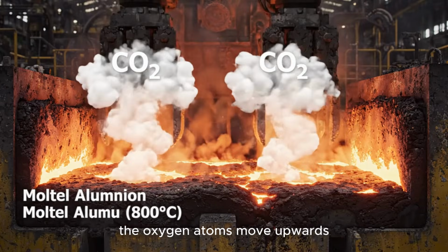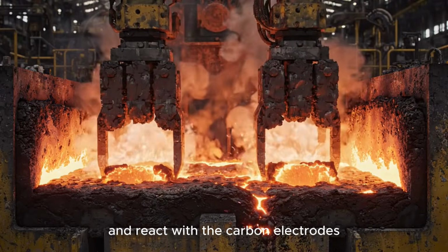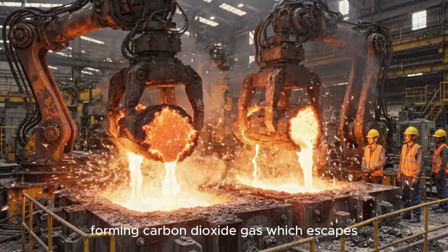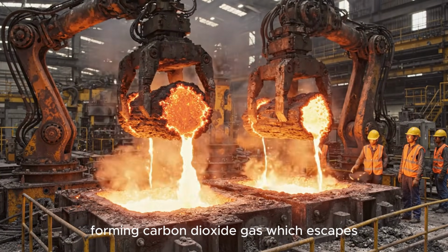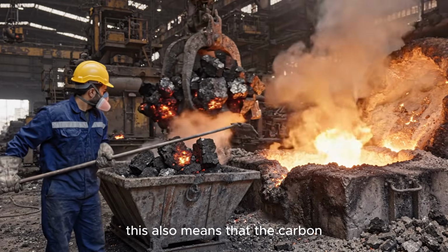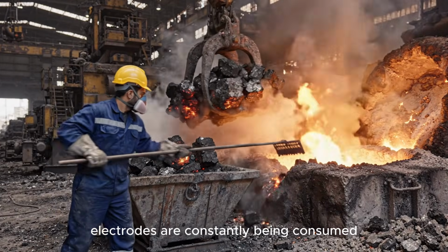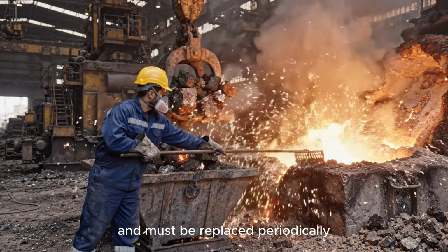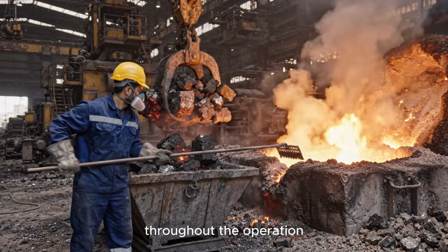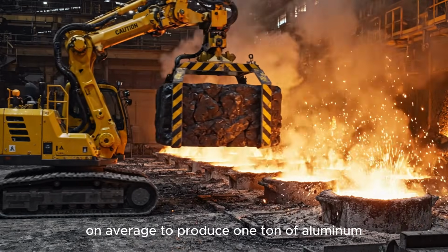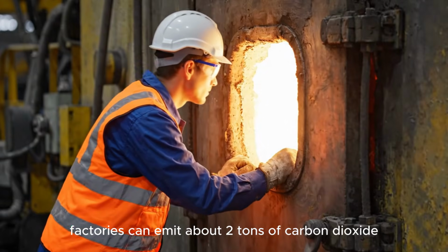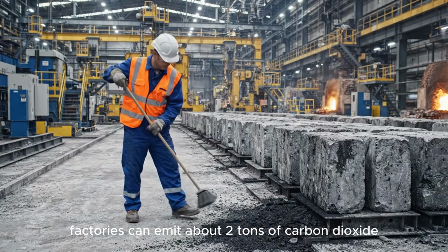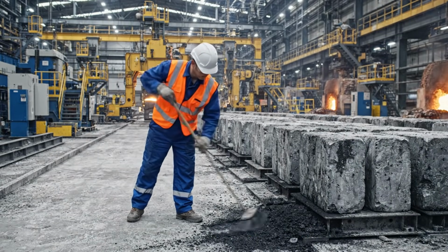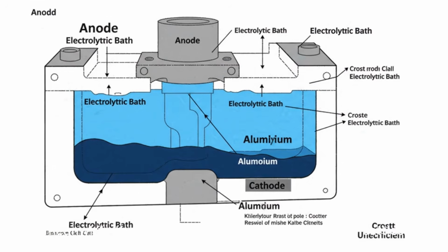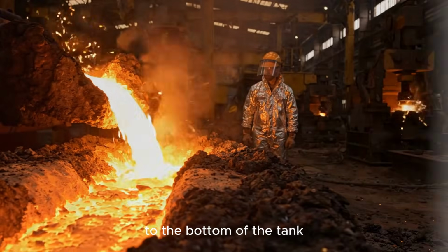The oxygen atoms move upwards and react with the carbon electrodes, forming carbon dioxide gas, which escapes. This also means that the carbon electrodes are constantly being consumed and must be replaced periodically throughout the operation. On average, to produce 1 ton of aluminum, factories can emit about 2 tons of carbon dioxide. Meanwhile, the heavier molten aluminum gradually settles to the bottom of the tank.